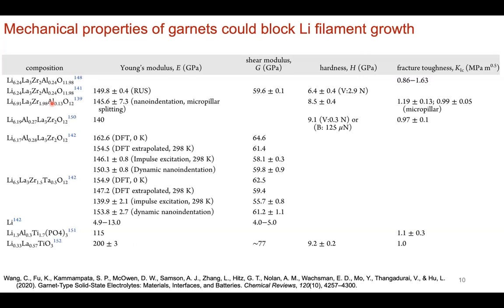So some of these authors are modelers. They are computational material scientists, computational chemists, along with one of the first people to really look at it, Thangadurai, to look at LLZO and actually lithium lanthanum niobate and tantalates. And so it is not beyond capabilities, but what are the current capabilities, right? So if you want to model lithium filament growth, that is a dynamic process. And typically that has to be modeled with perturbations to the ground state, right? So the molecular dynamics type of simulations need to include parameters that are not static, like density functional theory, right? If you deposit one lithium atom on, let's say, as an adatom, as a nucleation point to a surface, that is a good starting point as a very static model.